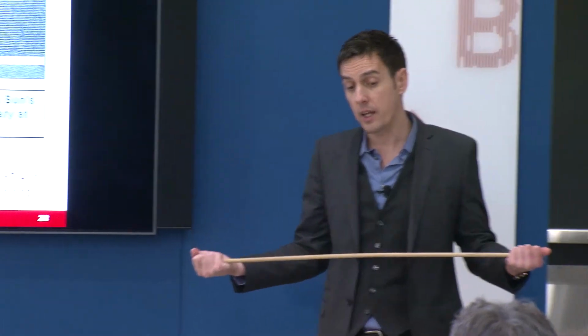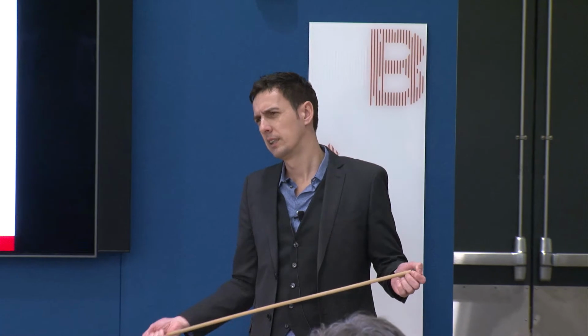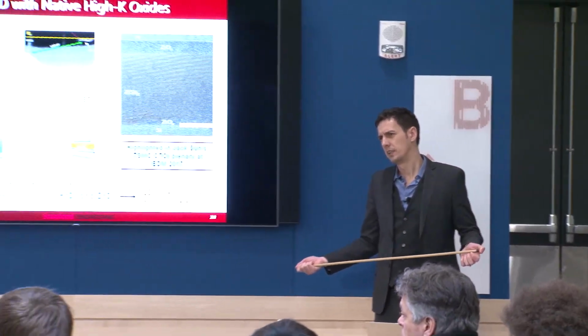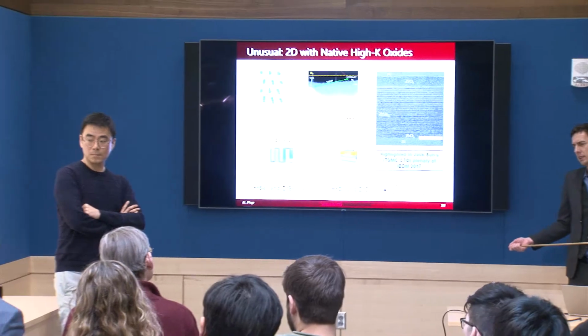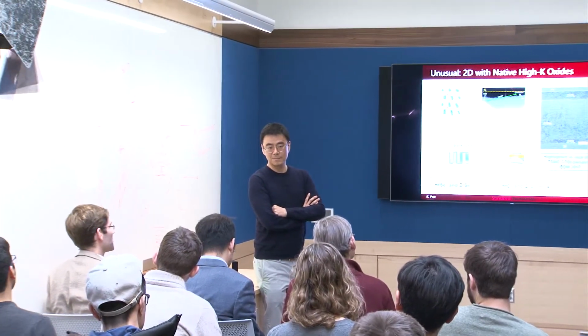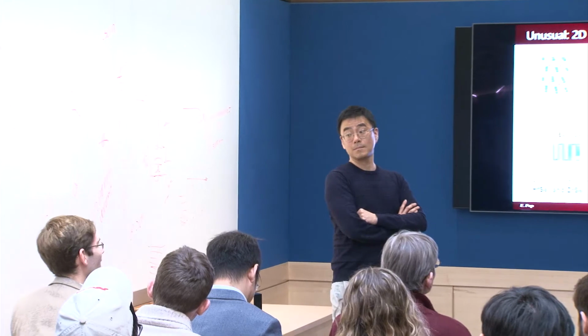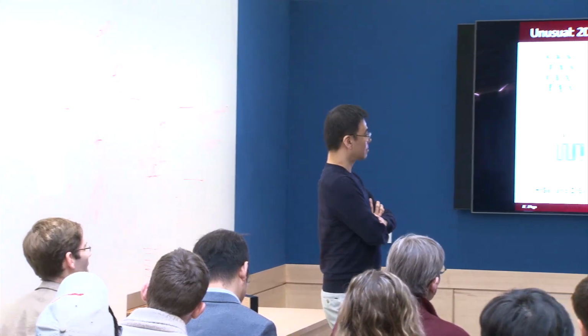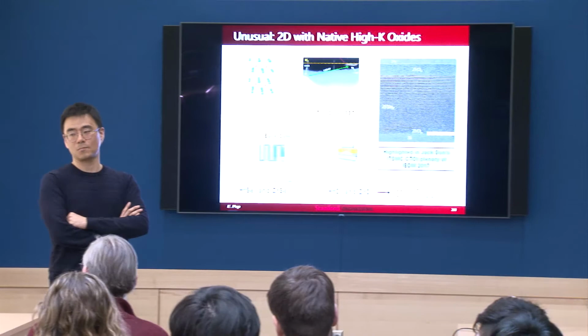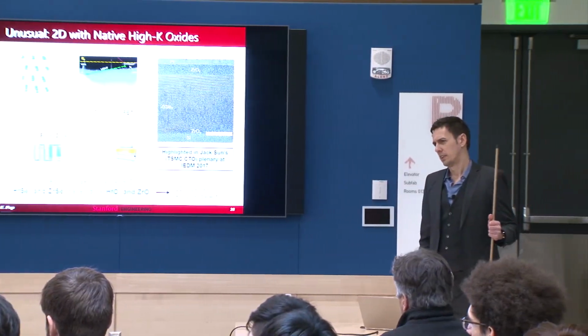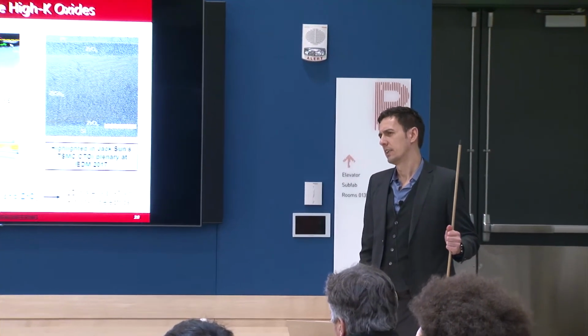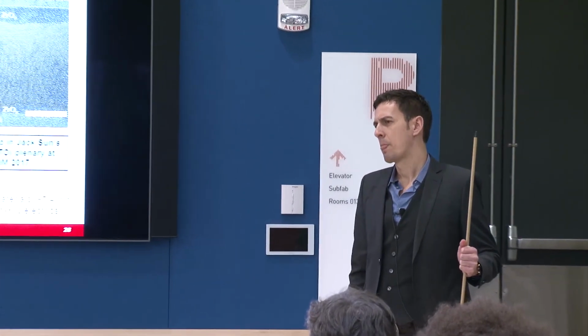But I agree with you in the sense that certainly having native oxide should give us better mobility in these materials. But to have a native oxide doesn't mean that you necessarily have good transport. For example, in gallium nitride, we really hate gallium oxide. So we try to avoid it in any way we can, even though it's a native oxide. How good is that oxide, though, as a high-K dielectric? It could be okay, but the mobility suffers, and you do have interface density issues.